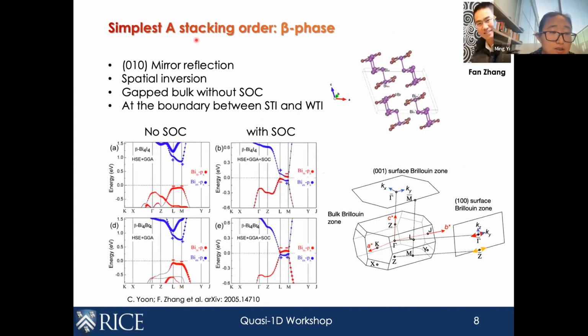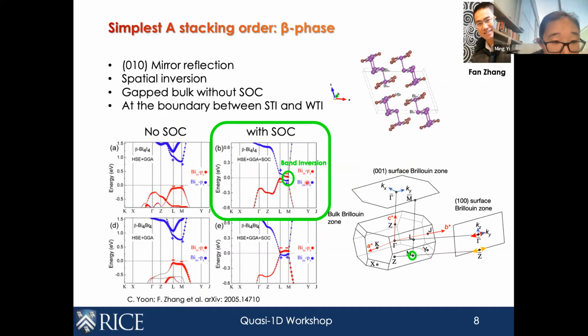So here, as Fan has also already demonstrated, if you carry out first principles calculations, very beautifully, these materials have a nice bulk band gap around the Fermi level if you don't include spin orbit coupling. There's spatial inversion symmetry, there's a 010 mirror reflection symmetry, and when we start to include spin orbit coupling, you can realize one of a couple different states. Depending on the size of the bulk gap at different momentum points, you can have the situation shown on top. Here, with this kind of bulk gap, you can have a single band inversion in the bulk states. What that means is that, if this is the Brillouin zone and you have a single band inversion, and we project it to different surfaces, we will have a single Dirac cone on each of these surfaces, and that will qualify this phase as a strong TI.